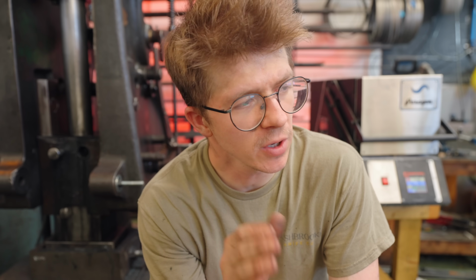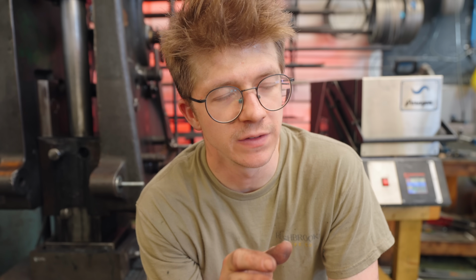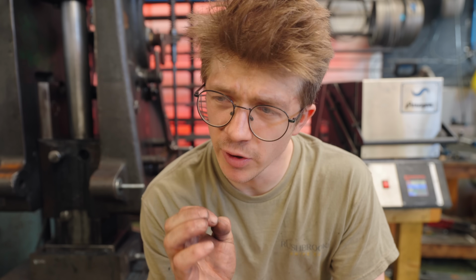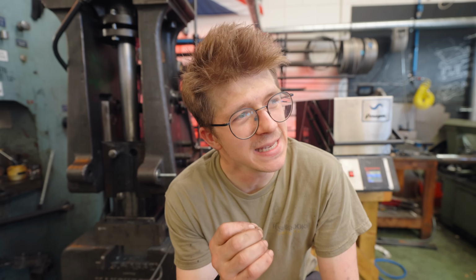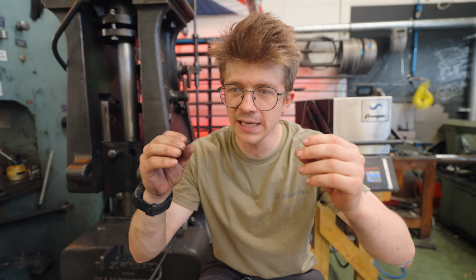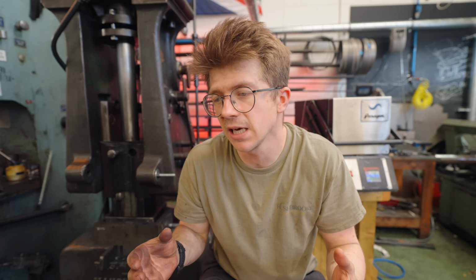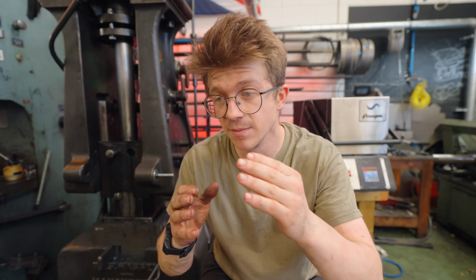Quick recap. Upon taking them out of the furnace at 1,050 degrees, we discovered, fortunately only at moderate speed, some liquid intermetallic compound. I'm a bit concerned about how that could have formed. Maybe we were deforming it too quickly and we ripped apart the nickel interlayer, exposing the hot titanium to hot steel. Maybe it was just the edges where there could have been some overlap and the titanium could have touched the steel. I'm not entirely sure.